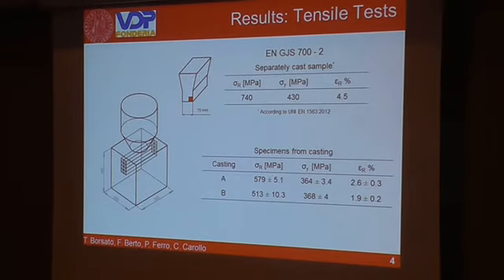In order to evaluate the mechanical properties of the castings, specimens were taken from the last to solidify zone, as represented in the figure. It can be observed that the mechanical properties of specimens from the castings are lower with respect to those of the separate cast sample. It is obvious because those specimens were taken from the last to solidify zone. There are also some differences in ultimate tensile stress and elongation at failure between the 2 castings.